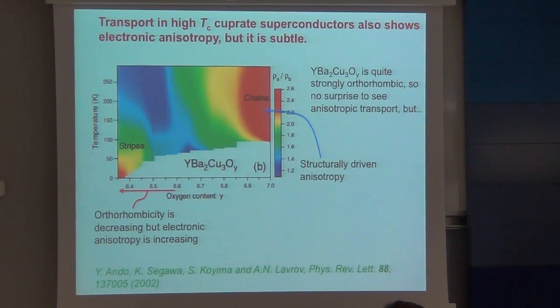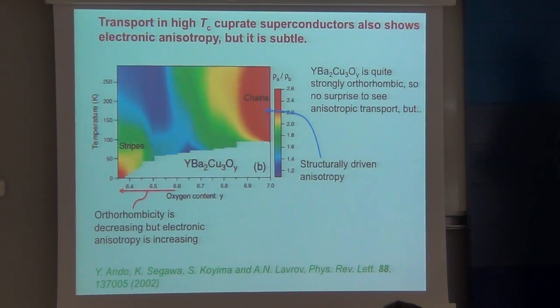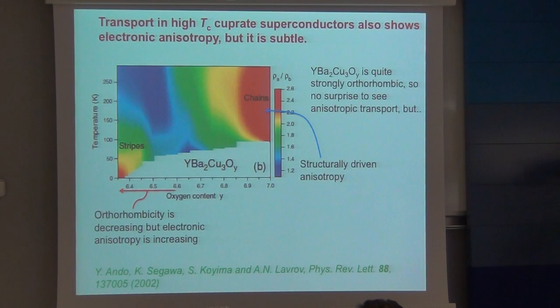It turns out 10 or 15 years later that you don't find static stripes, but this anisotropy is now relatively widely accepted to be a feature of the conduction electrons and coming from interactions within the conduction electron gas. And it's likely to be one of these melted stripe type nematics, because this is quite a strong coupled system.